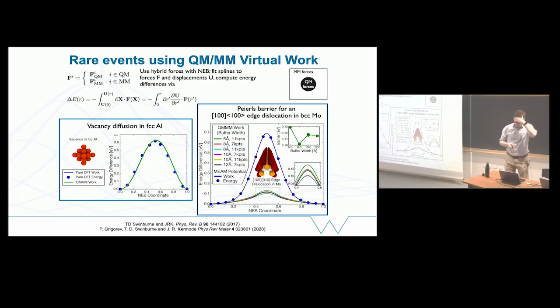Here's another example of a dislocation in molybdenum. And again, here you can really see how we can converge this barrier with respect to the buffer width, so that layer of padding that we place around the quantum region. It's really expensive to do so, but if we make the calculation, that quantum region more and more well padded, the barrier does settle down and we get 0.1 electron volts. So we can compute energy barriers in really big systems with really complicated things going on.